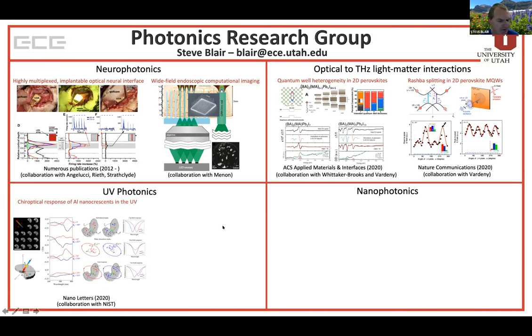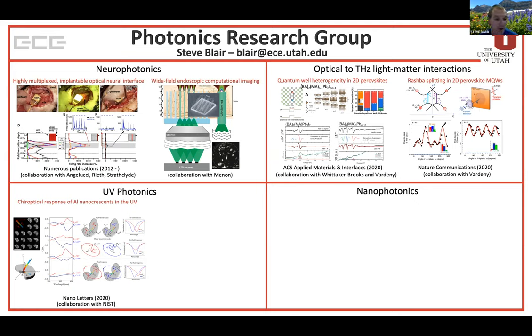In the area of UV photonics, we've focused a lot on UV plasmonics — the use of deeply sub-wavelength structures producing a very strong, tightly confined resonance response in the UV spectral regime. Some recent work there was looking at the chirooptical response, an engineered chirooptical response of aluminum nanocrescents in the ultraviolet. Chirooptical response consists of optical activity and circular dichroism absorption contributions, and we have ways of engineering both to enhance chiroselective spectroscopy, which is extremely important in the UV regime when dealing with biomolecules.